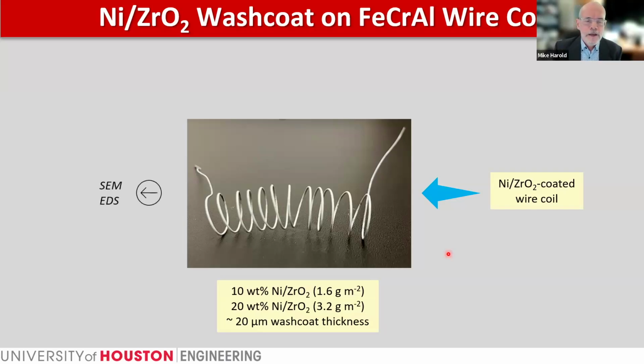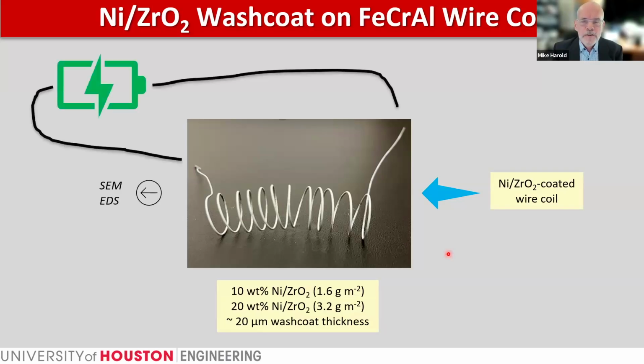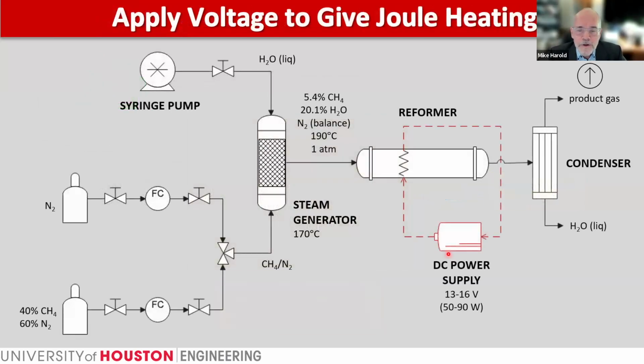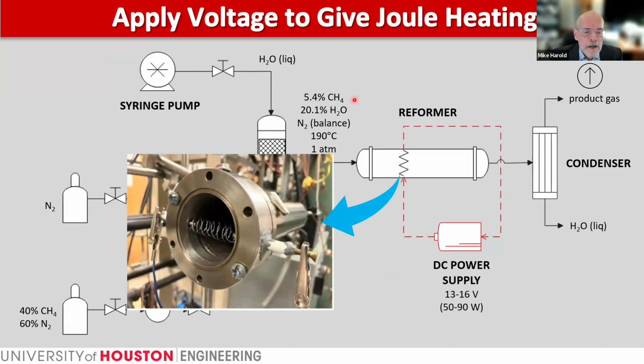So we take that wire and then do some characterization, bring the wire into a reactor and apply a voltage across the wire with the purpose of heating up the wire and carrying out the chemistry. This is a layout of the straightforward reactor system that Elmer has constructed. We basically carry out SMR in what I'll call a single wire reactor using a somewhat diluted methane steam reforming feed of nominally 3 to 4 steam to methane ratio. We do some preheating, and then the bulk of the heating is done by the ohmic process, the Joule heated process. This is a picture of the coil spanning the cross-section of the tube.